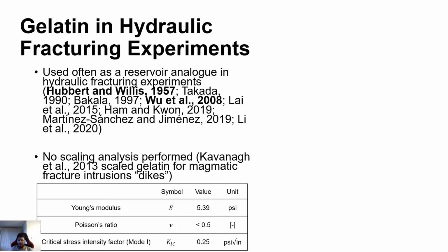gelatin at various concentrations. So I used her correlations to evaluate the mechanical and fracture properties for my gelatin blocks from the conditions I used during my master's degree. And I find the Young's modulus to be 5.39 psi, the critical stress intensity factor for mode 1 cracks to be 0.25 psi square root inch, and the Poisson ratio is constant regardless of gelatin concentration and approaches 0.5, which is the upper limit for a very elastic material, that is gelatin.